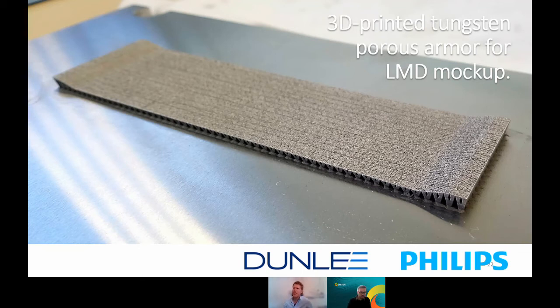There is one challenge with printing, though, also a very technical, practical challenge, is that currently these printers work with a powder bed. So there is a flat bed of powder, and you pull the laser across that, and then you swipe over a fresh layer of powder. But this bed has to be perfectly flat. But the diverter pipes may not be perfectly flat, because they are in assembly, maybe the tolerances are just not good enough. So it would be great if we can think of a way to fix that.